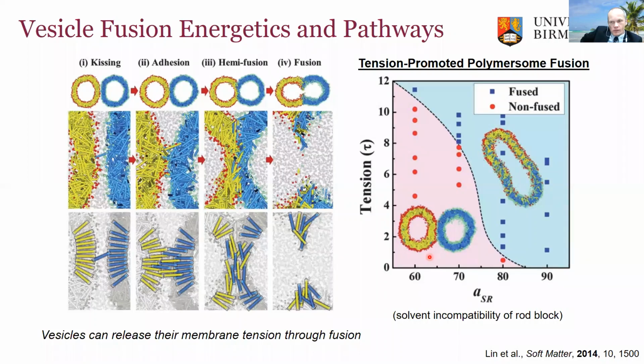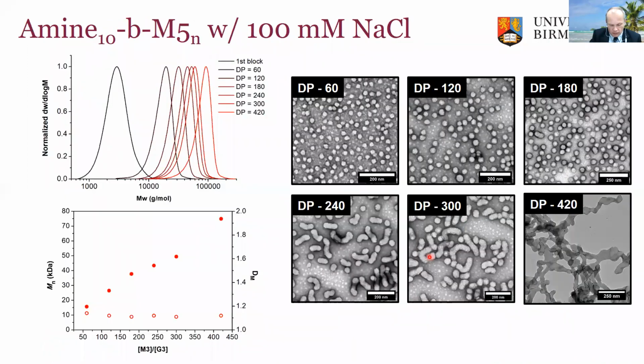So one of the things we thought was, well, if you remember for the amine system, we didn't see any polymersome fusion. We just saw that they were retained as spherical constructs. So we proposed that with the amine-based system, we were not able to get particles adhering to each other and maintaining close contact, because of the charged nature of the amine. So we thought, if we shielded those amine interactions, would we be able to see fusion? And the answer is yes.